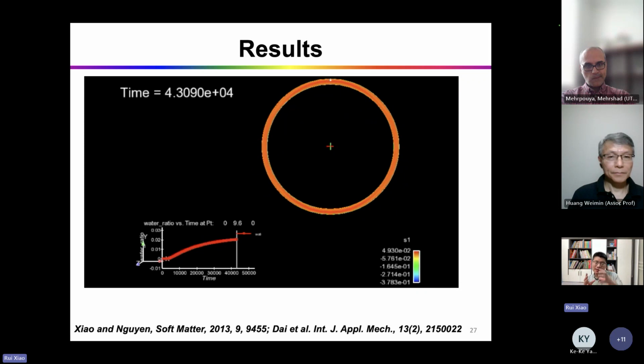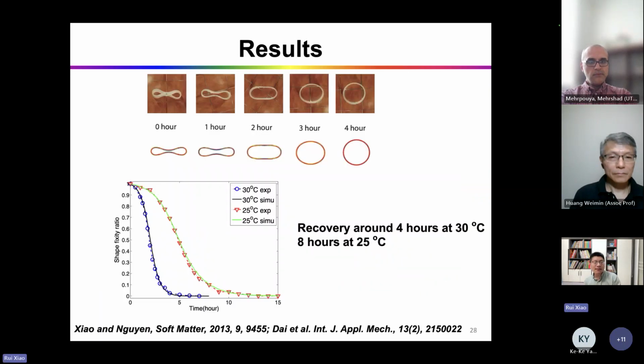So it's possible that the outside is wet while the inside is still dry. In that case, you will have no shape recovery until the inside also has some solvent, then you have the shape recovery. So this is our model and our experiment comparison.